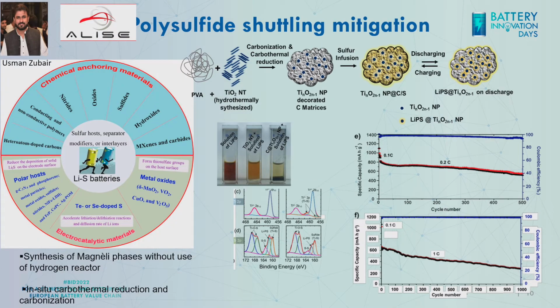So what can we do in order to solve this issue? There are several approaches. If you check the literature, you will find a lot of publications with different possibilities. But let me summarize them in 2 different classes. One class is the chemical anchoring of the materials, which means that we are using some compounds within the cathode that trap the polysulfides and keep them inside the cathode. So when they are formed, they still remain in the cathode and cannot flow through the cell.